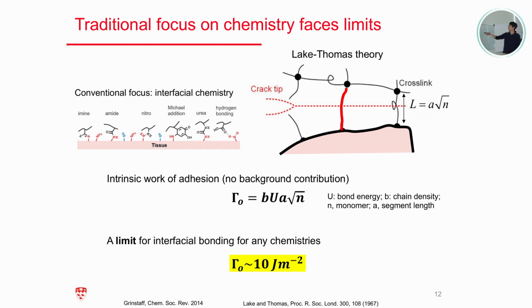So put them together, we use some representative numbers, and we calculated the limit for this gamma 0 is on the order of 10 joule per meter square. So that is comparable to the adhesion performance you actually measure from the surgical glue.